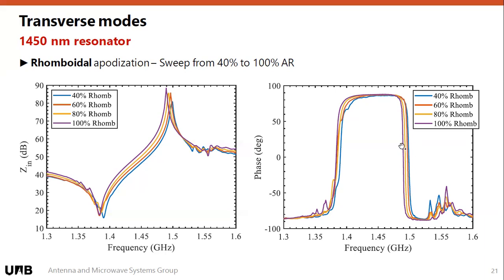So while FS remains almost unchanged, your FP is actually moving just by changing the apodization ratio. This is something we don't really want because we were aiming for coupling. So we want to clean the spurs, but get the maximum coupling. Actually, you can also see that you might even get stronger modes above FP. So this is something in which we need to find an optimum. And the optimum, in the end, is at the 60% apodization.